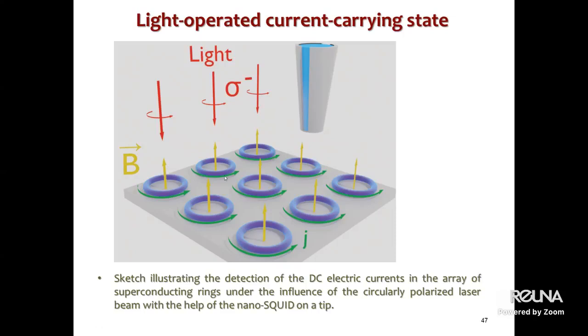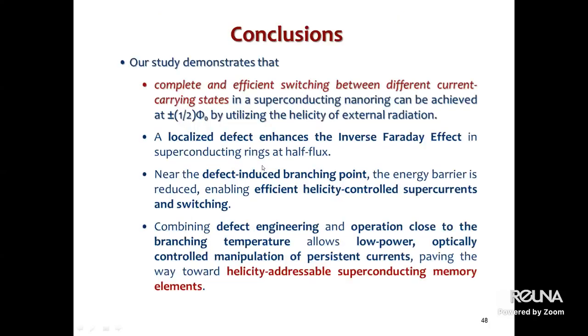And finally, I'm coming to the conclusions. So what we did, we demonstrated that complete and efficient switching between different current carrying states in a superconducting nanoring can be achieved by utilizing the helicity of external radiation. And I showed that a localized defect to some extent enhances the inverse Faraday effect in superconducting rings at half quantum. So basically, combining defect engineering and operation close to the branching temperature allows low power, optically controlled manipulation of persistent currents. Thank you for your attention.